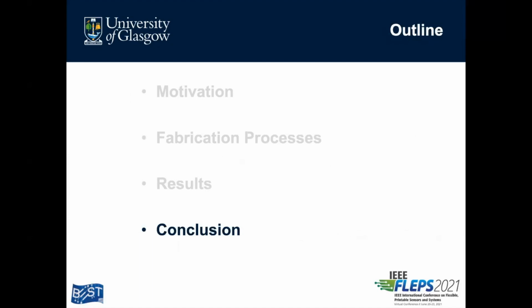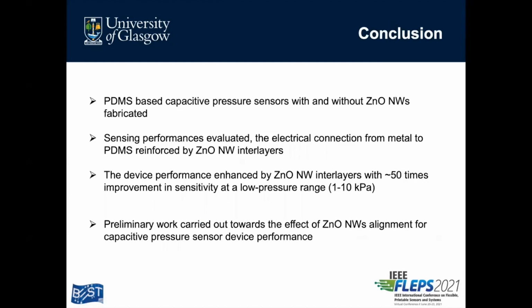In conclusion of this work, we fabricated two PDMS-based capacitive pressure sensors with and without zinc oxide nanowires. Then we evaluated the sensing performances and observed that the electrical connection from the metal to PDMS could be reinforced by introducing zinc oxide nanowire interlayers. By taking advantage of zinc oxide piezoelectric properties, the device performance was enhanced by zinc oxide nanowire interlayers with 50 times improvement in sensitivity at a low pressure range, which was 1 to 10 kilopascals.